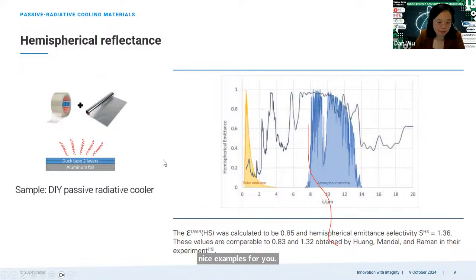If you have an FTIR spectrometer and the accessories in your lab, you can also do this as a practical experiment for your students. And the experiment itself is quite easy. You can use aluminum foil as the substrate, and then put two thick layers of duct tape on top of the aluminum foil. And why this? Because aluminum foil is actually a very good reflector of light at any wavelength. And the duct tape, with enough thickness, is a polymer, so you have a very strong absorption in the mid-infrared range. And this is exactly how we should design passive radiative cooling.